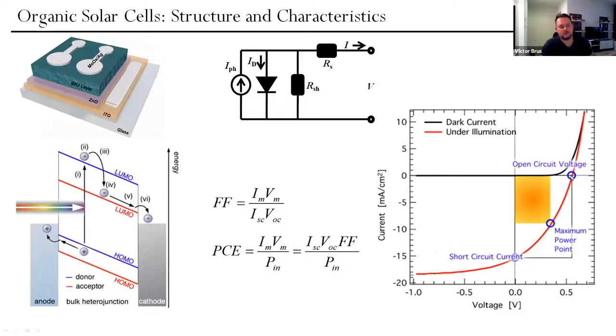Also, it depends on generation and recombination processes, because open circuit voltage is defined from a physical point of view as the gap between quasi Fermi levels for electrons and holes in the active layer. And the position of these quasi Fermi levels will depend on the concentration of photogenerated non-equilibrium charge carriers in the active layer. That means the more photogenerated charge carriers we generate in steady state conditions, the higher their concentration will be, and the larger VOC will be, which cannot be larger than the band gap because that will be the limit, a maximum possible value.